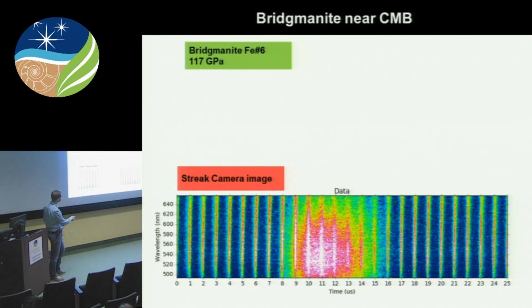So for these types of experiments, we're using a completely different detector, which is called a streak camera. So this is an example of a streak camera image. What you see here are the supercontinuum pulses, the white laser pulses, as a function of time, how they traverse our sample. Here you can see that around the 8th microsecond, you see this big blob of thermal emission coming from the hot sample, just simply because the sample is hot during that time. And then the y-axis tells us something about the optical properties of our sample at such conditions.